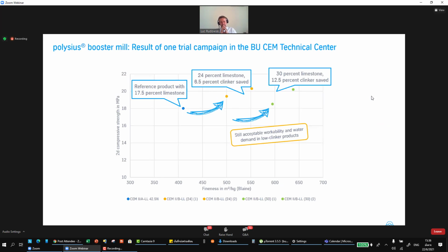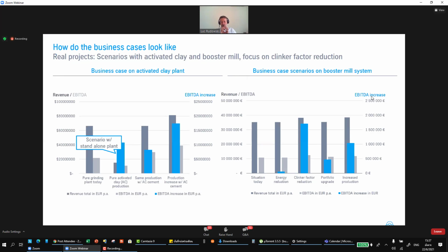The results, as you can see here, is that we ground the clinker finer in order to increase from this reference limestone cement, with 17.5% limestone in the cement, up to 24 and then to 30% limestone cement. And in fact, the results are extremely promising, because you can see here the test at 2 days compressive strength, but that's the same at 7 days and 28 days, with still very acceptable workability and water demand. So I think the potential of reducing the clinker factor by about 10 points is easily achievable, which is on top of what you can do with LC3 cements. And for both technologies, the business case is extremely strong.